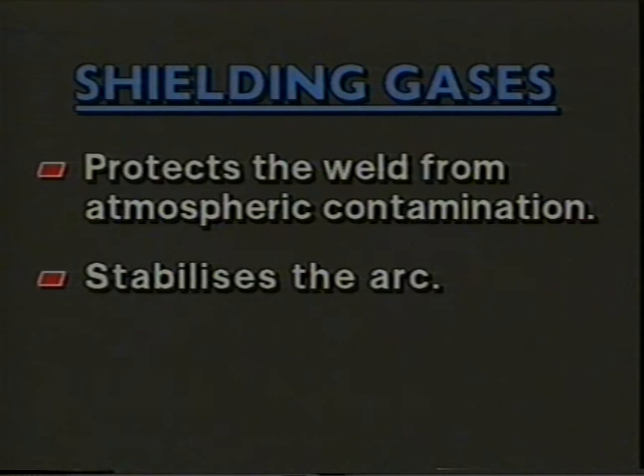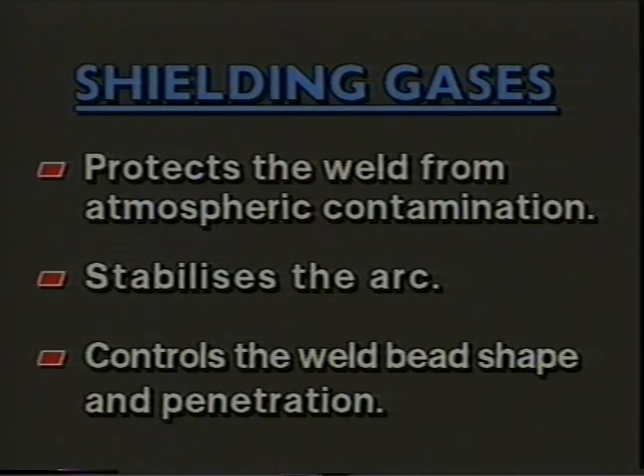Small additions of reducing gases, such as hydrogen, can be added without affecting the electrode. It stabilizes the arc. In these stainless steel welds, you can see that an argon-helium-hydrogen mixture, as used on the right, gives a more stable arc than argon, as used on the left. It controls the weld bead shape and penetration.